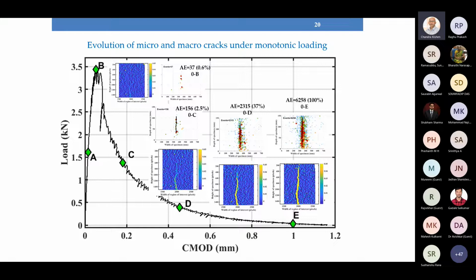At the peak load, this is 0 to B. At the peak load, we have the AE events. 37 acoustic emission events have occurred. That is less than 1% of the total. The total at failure were about 6,258 events or micro cracks, and only less than 1% have occurred when the peak load has reached.